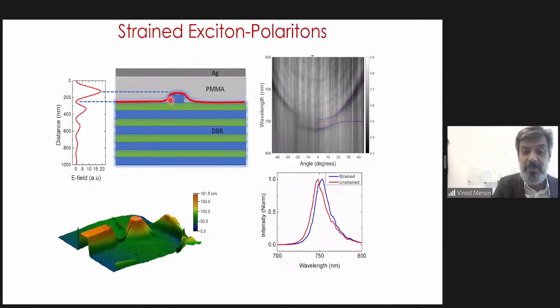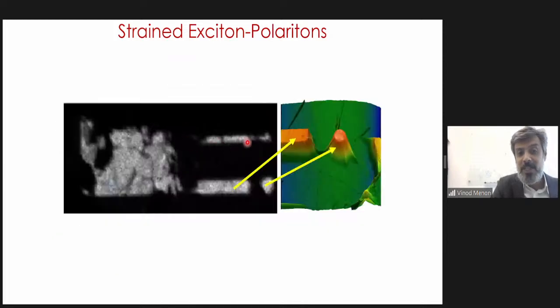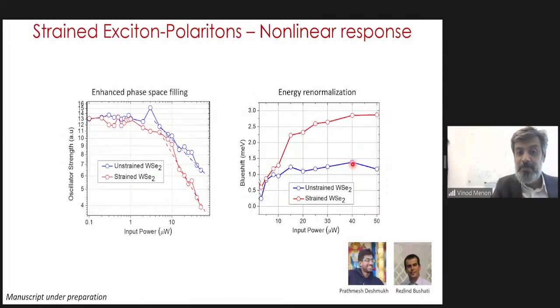And so what we've done is we've created a cavity with pillars where we get maximum field here. And you can see the light-matter coupling happens on top of these pillars or in these ridges. So this is an atomic force microscope image that shows how the 2D material is wrapped around these pillars. And the end result is that the blue shift or the nonlinear response is much more enhanced on the strain system. So there's a nice exercise in where strain is used to localize carriers. And by using that, you get an effective nonlinearity, which is larger than what you would get if it was unstrained.